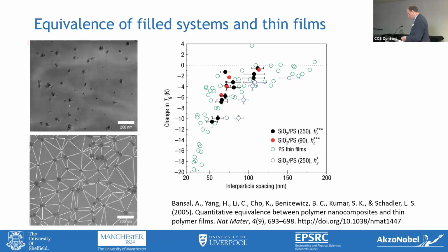The interphase, on this basis, even in a chemically pure system with no chemical heterogeneity, that's my answer to the question, really. It's of order 10 nanometers.